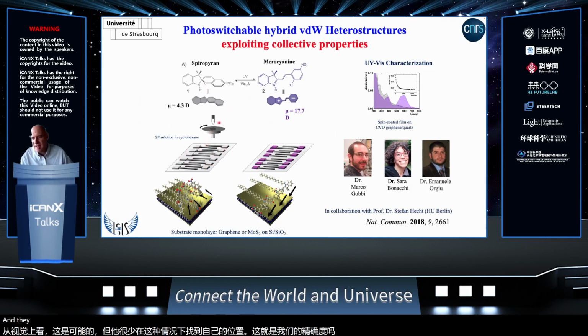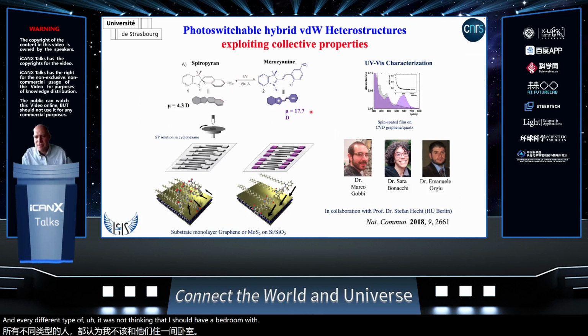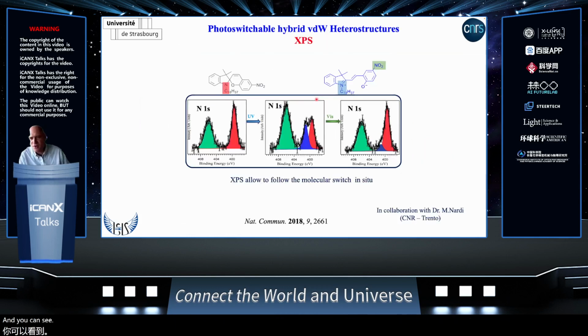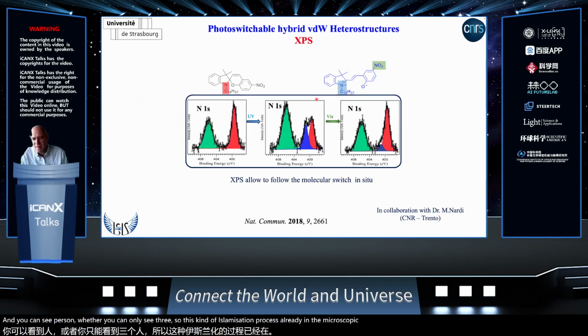And then on the surface, we can in situ change the state of the head group from spiro to mero and have a different type of electrostatic interaction of that group with the 2D materials underneath. So this was work done by Marco Gobbi and Sara Bonacchi. And you can see, first of all, that you can trace this kind of isomerization process already on the macroscopic scale by XPS.